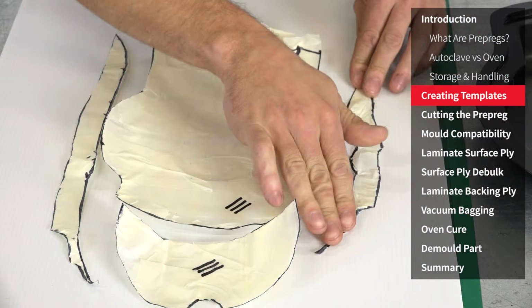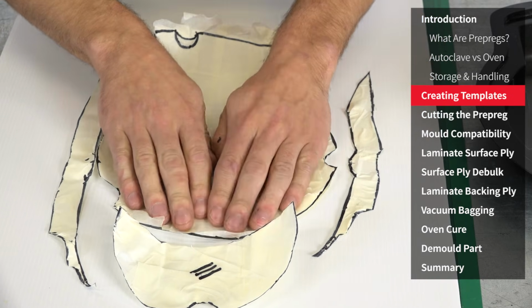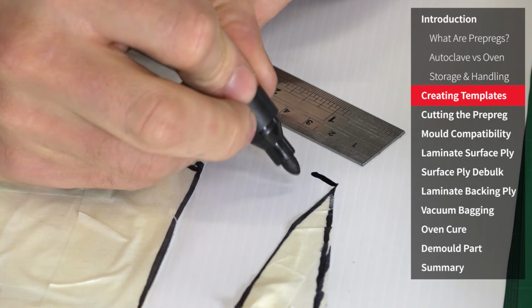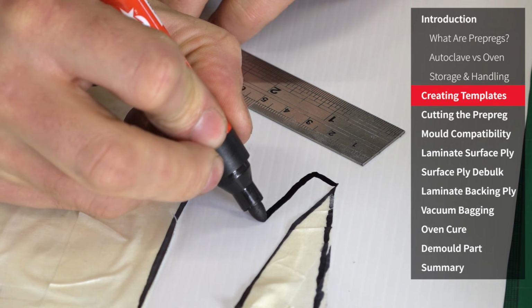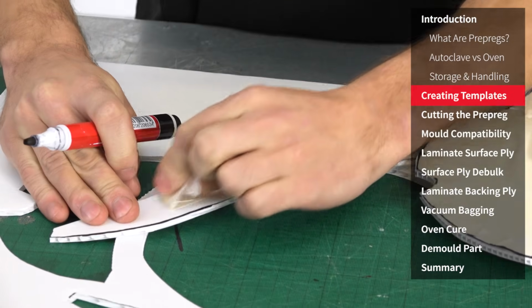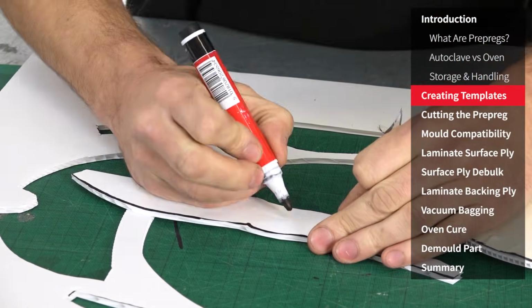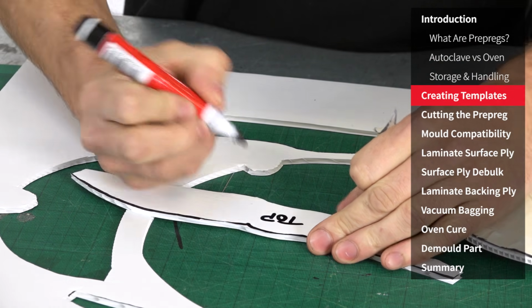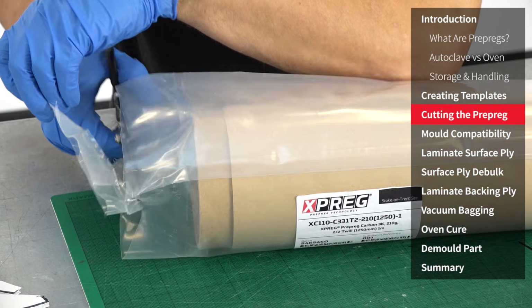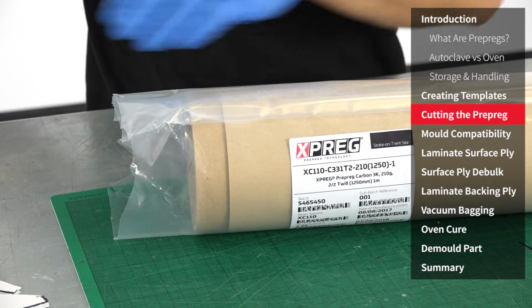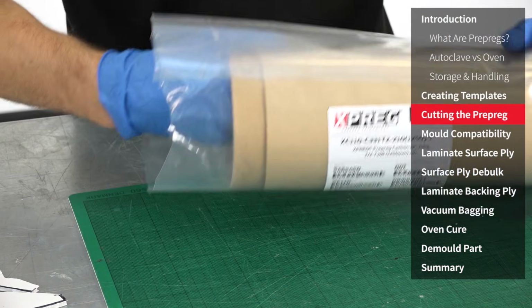The sections should then be flattened out as neatly as possible and extensions added for any overlaps required between the pieces. After cutting, mark the templates as required for identification and orientation. Now the pre-preg is fully defrosted, it can be removed from its sealed packaging. The templates can then be nested onto the material and marked out.